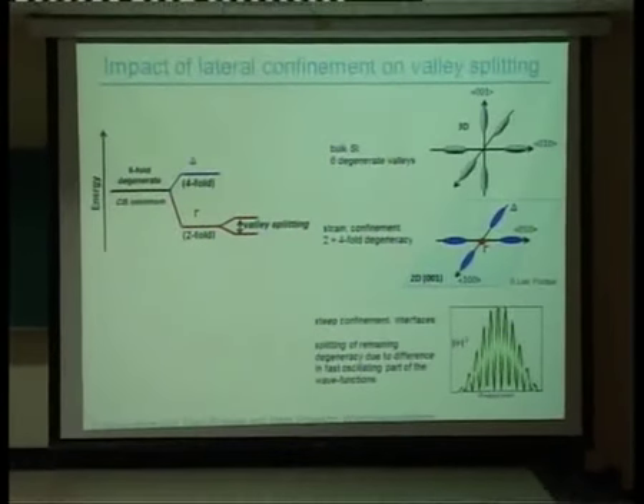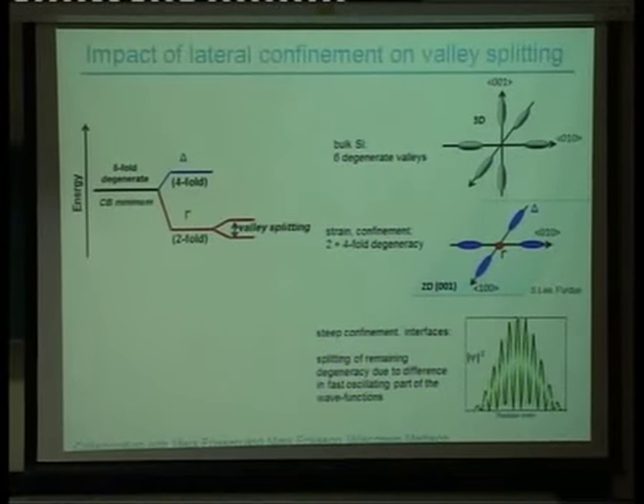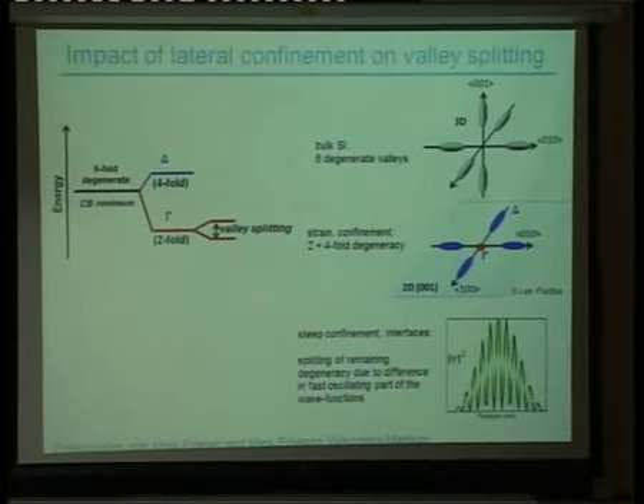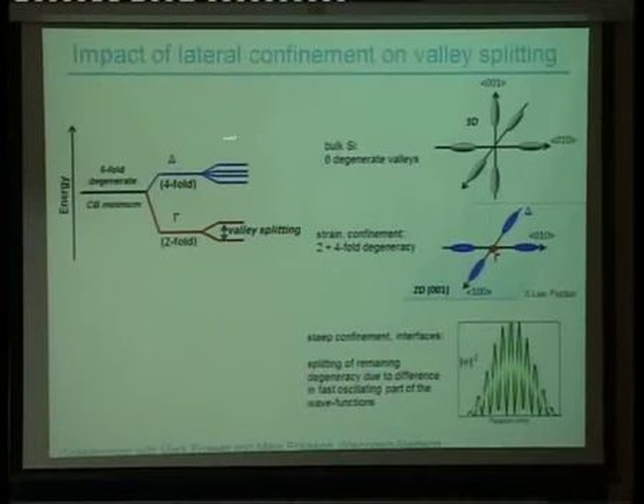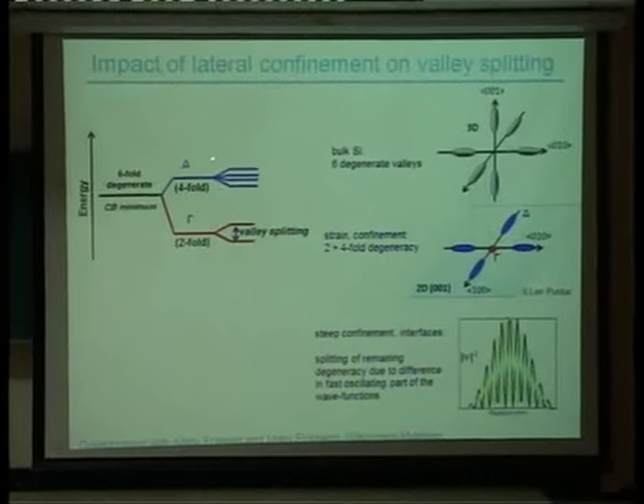So you've got this very strong vertical confinement, which basically breaks these 6 degenerate valleys into the 4 deltas and the 2 gammas. Because of the valley oscillations, we get this breaking in the vertical direction from the strong confinement. But now, because of the STM patterning, we're also very strongly confining abruptly in the lateral direction. And that basically means that we also get valley splitting in these delta bands.